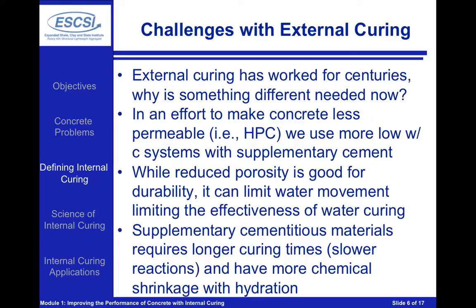Now, one of the big benefits of using these higher performance concretes is they limit fluid movement inside of the system. And as we just talked about on the previous slide, by limiting fluid movement, this can actually make it harder to get our curing water into our concrete. The second reason why we're starting to see a big increase in discussion of the potential for internal curing is because as we move to using more and more supplementary materials, these materials are going to require a longer curing time because they're less reactive than our conventional cements. This means we're going to need to keep water in that system for a longer time, and instead of ponding the systems for 2 weeks, 3 weeks, or 4 weeks, maybe we can supply that water in a different way. In addition, a lot of these supplementary materials have more chemical shrinkage than a classic Portland cement, and this is another reason why we would want to supply additional curing water.